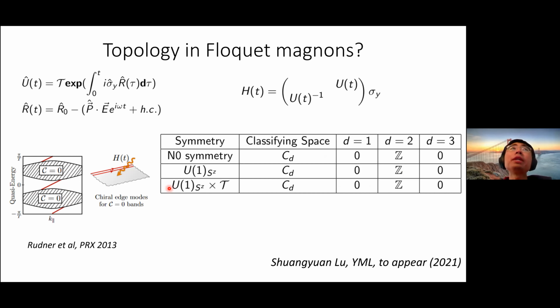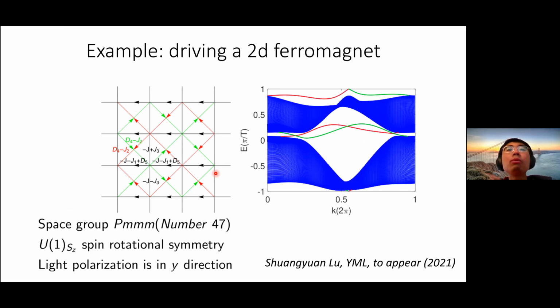What we have shown is that we considered two examples. One is a 2-dimensional ferromagnet—this is quite generic, what I've shown you is a specific square lattice example. For this 2D ferromagnet, you drive it using light with a polarization along a certain direction, in this case the y direction, along one of the axes of the 2D system. You can end up with a system where you have this chiral edge mode between the two bands, and each band, again, has Chern number zero. So it's intrinsically Floquet topology in such a system.